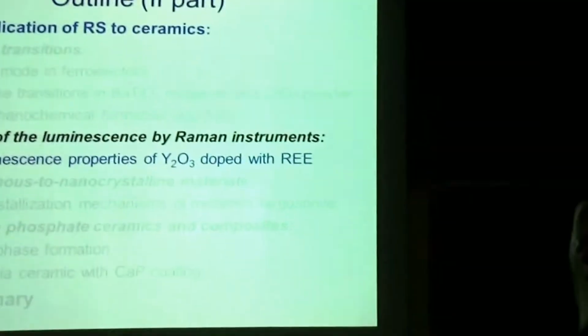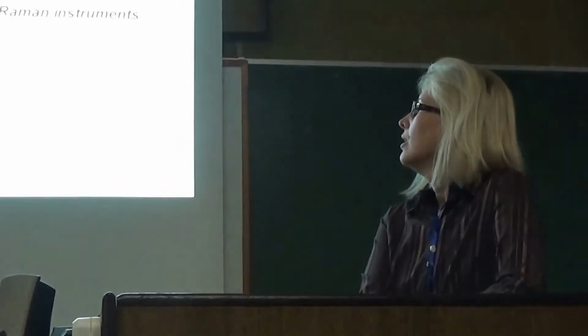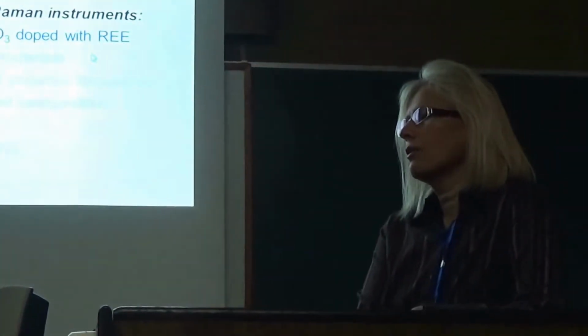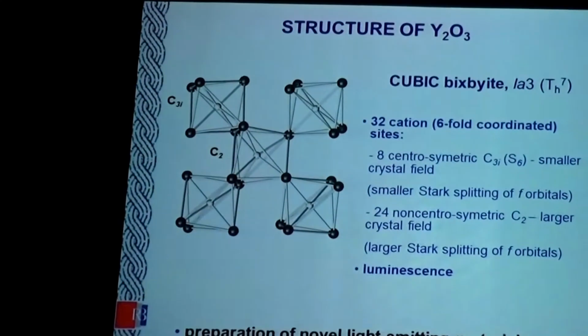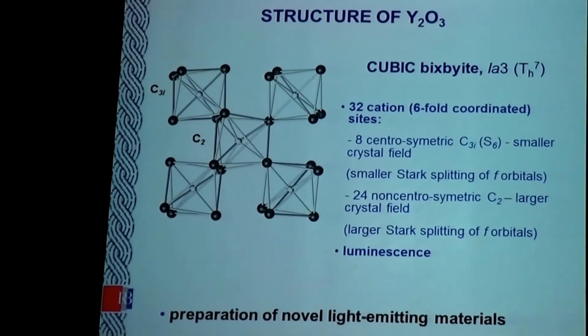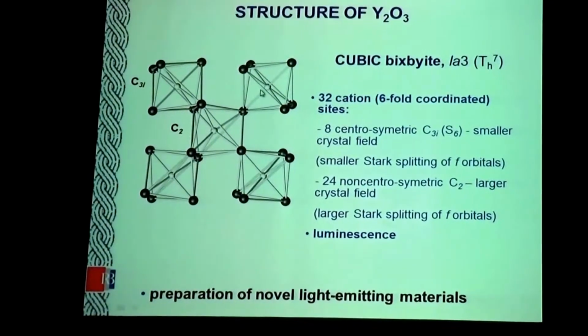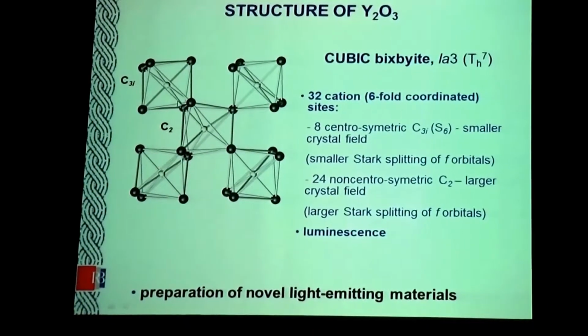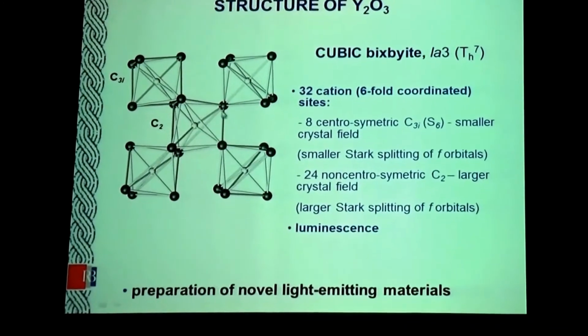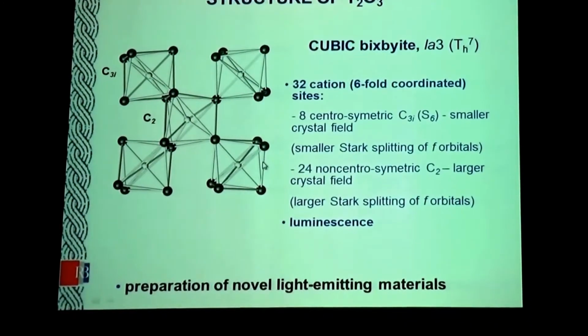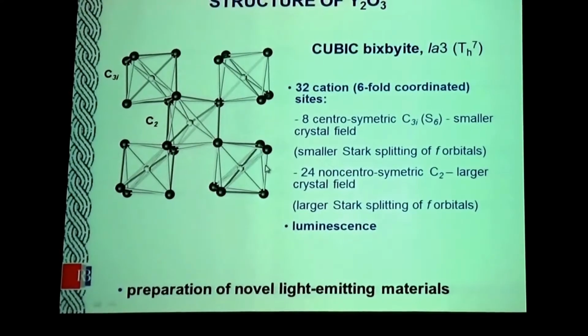However, we can use our instrumentation for measurement of some completely different phenomena. We measure luminescence properties of yttrium oxide doped with rare earth, or we can also observe very small impurities of rare earth. What is going on? When you put a rare earth oxide element, some ions, into the crystal lattice of, for example, yttrium oxide or any other matrix, you will have stark splitting of f orbitals due to the crystal field of your crystal.